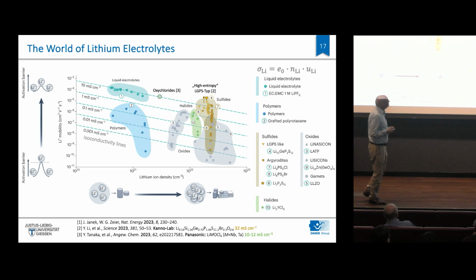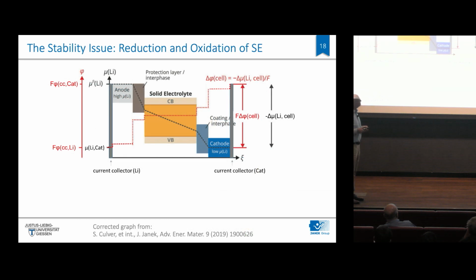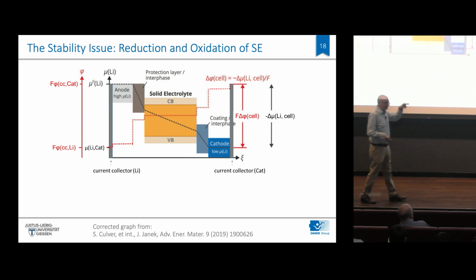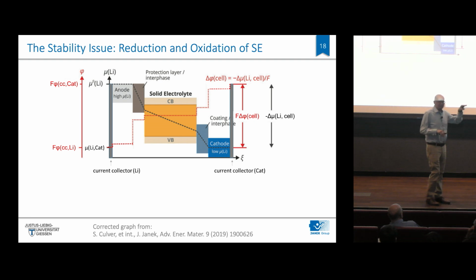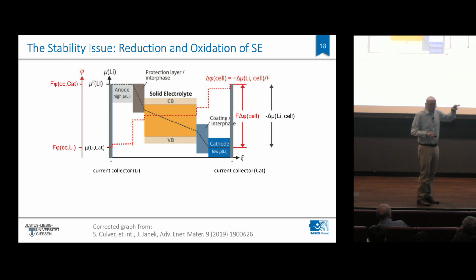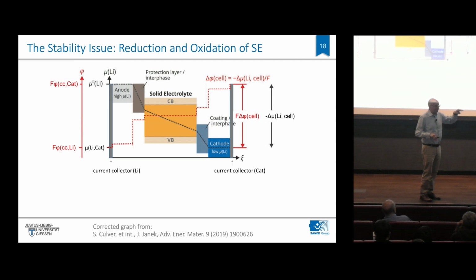What is more an issue, in fact, is the stability, because the electrolyte is in contact with the negative electrode and the positive electrode, and in the charged state, the cathode has, in physics terms, a very, very low Fermi level. It's extremely oxidizing, and at the anode side, extremely reducing. The voltage of lithium-ion batteries, typically in a charged state, is 4.2 volt. Water is being decomposed at 1.2 volt thermodynamically. So electrolytes really are exposed to extreme chemical forces, and that's something we investigated quite in depth,